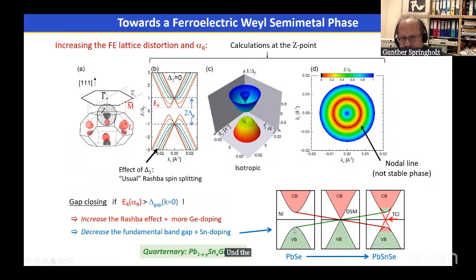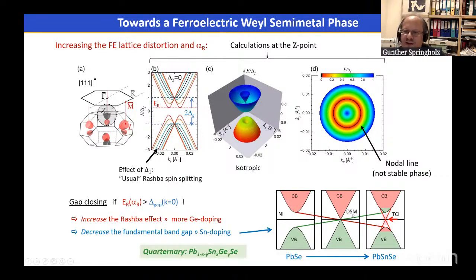This can be achieved by adding tin to the system. So if we go from lead selenide or telluride to lead tin telluride or lead tin selenide, the band gap of the material decreases and crosses zero at a certain concentration, which is about 16% for the selenide system and 36% for the telluride system. Actually, in this direction, we have a transition from a normal insulator semiconductor to a Dirac semi-metal system to an inverted band structure showing topological crystalline insulator properties. But here we remain in this regime where the band gap of the system is very small, so it is easily achieved that the Rashba energy is larger than half of the band gap.